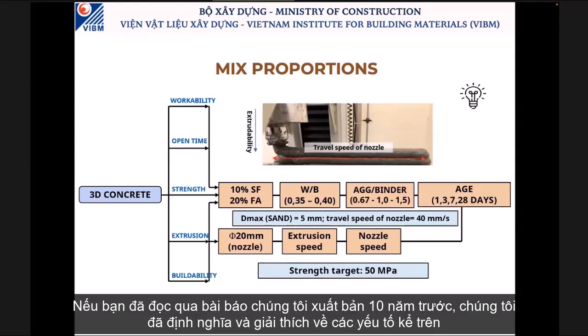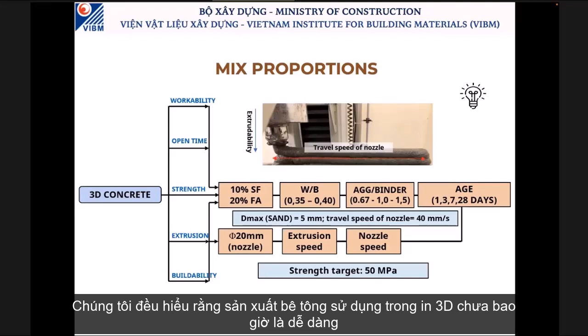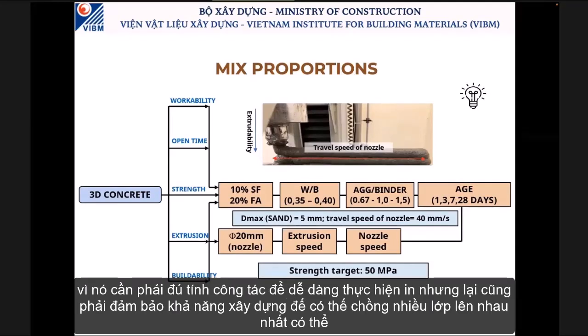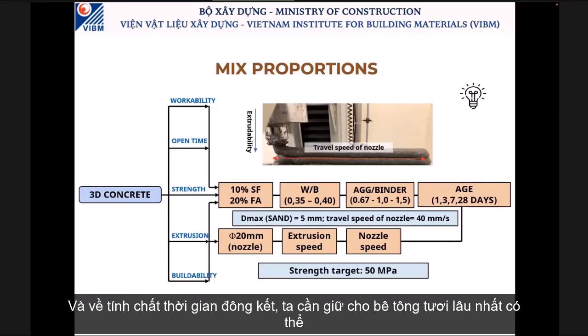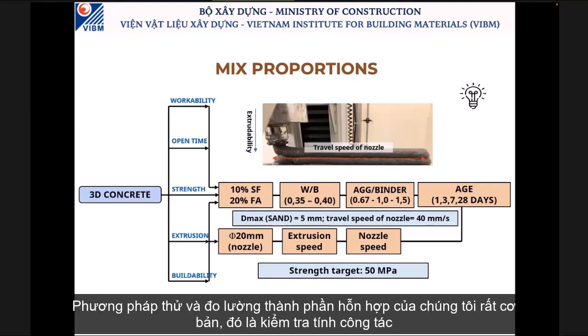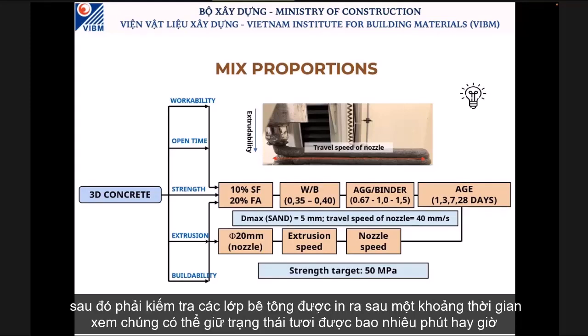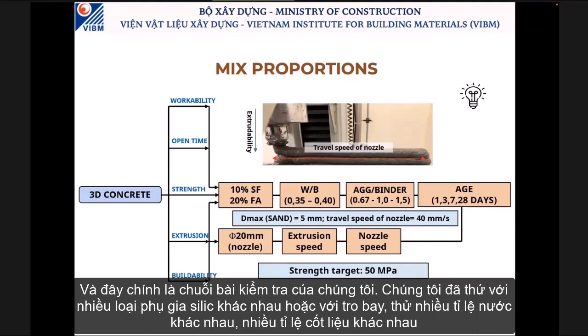If you have read the paper we published 10 years ago, we defined buildability, extrudability, and open time. And we all know that 3D concrete is a really challenging sort of concrete because it should be very good in fresh properties for extrusion, but it also needs to have good buildability. We define that as being able to build as many layers as possible. In open time, we need to keep the fresh concrete as fresh as possible. A very basic measurement is we test workability, and we need to test it after time intervals to know how many minutes, how many hours it can keep the fresh properties.